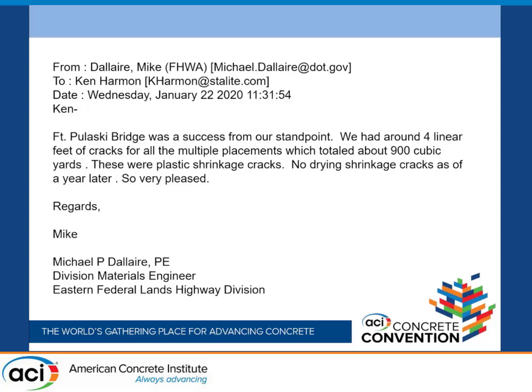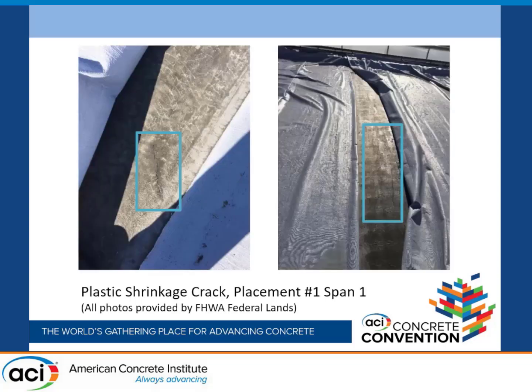They did a crack survey about 4 months after they completed all of the 13 spans, which was about 7 months after the first deck pour, and they didn't find any other cracks after 4 months or after 7 months.